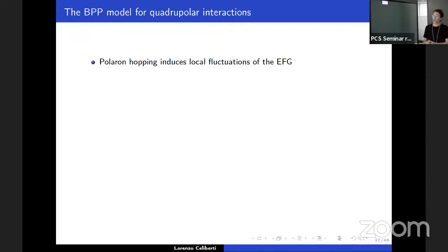fit this data with a model where we consider, if we have something related to polarons, polaron hopping. This displacement of charge is basically changing lattice distortions. Okay, so you have basically fluctuation of the electric field gradient around the nucleus. And this can be probed because the sodium nuclei in our material have a spin larger than 1/2, so they have a quadrupolar moment, which couples to these electric field gradient distortions.